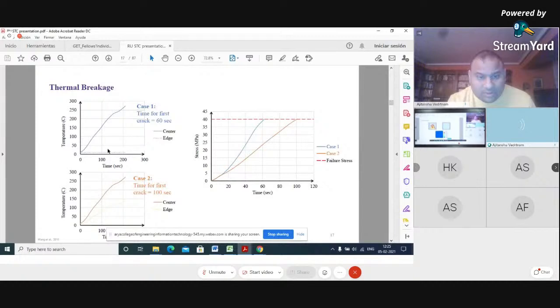You can see in the first case, once there was a restriction or a frame to the window, the glass was broken after 60 seconds. But once there was no restriction around, and we kept the temperature rising from 0 to around 270 or 280, the glass was broken after 100 seconds. So you can see there is a significant increase in the time once there is no structure and no frame